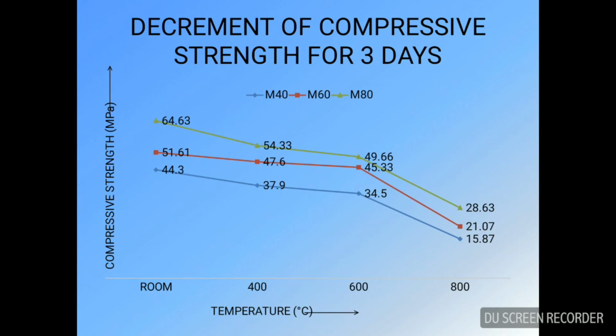Now this graph shows the decrement of compressive strength after 3 days of curing. The strength for M80 is denoted in yellow color, for M60 in red color, and for M40 in blue color. As you can see, the strength of M80 decreased from 64 to 54 after being heated at 400 degrees Celsius, while for 600 it decreased to 49, and at 800 it decreased to 28.